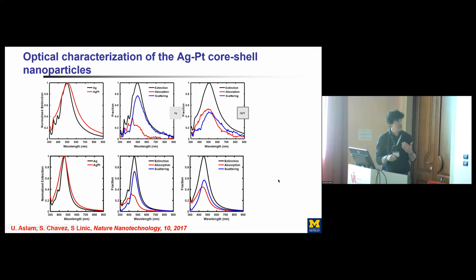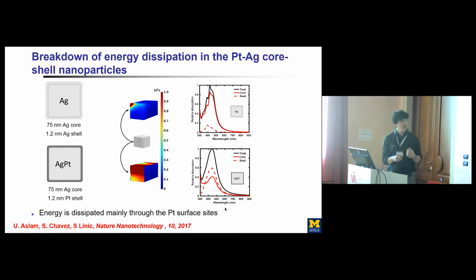We have also done some simulations, basically just looking at whether these simulations are mapping out these experiments, and we see exactly the same situation. We see that scattering is much larger for pure silver. As we deposit a very thin shell of platinum, the absorption starts dominating this process. And we can use this modeling now to ask a question: how much energy goes through platinum? How much absorption do you have on platinum in these core shell systems compared to pure silver?